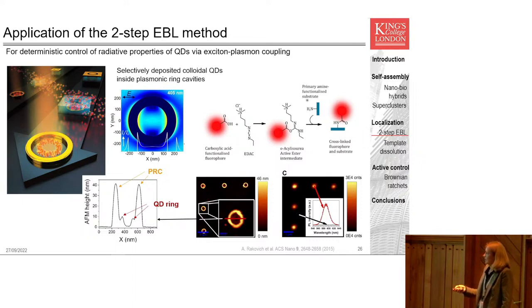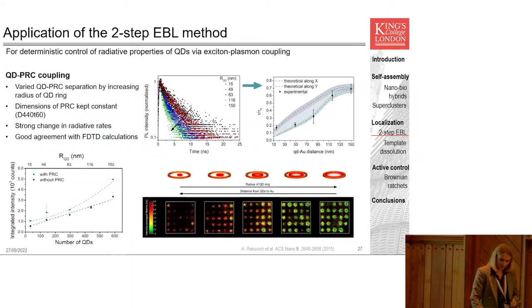And so in the same method, you can then place quantum dots on the inside of this plasmonic ring cavity to make them couple to the plasmonic structure. And here I'm showing an AFM image of the plasmonic ring cavity, which is 40 nanometers high, which is these two peaks here in cross-section. And there's a ring of quantum dots deposited inside, which is this little blip here in the AFM data as well. You can clearly see that you get emission from the quantum dots, so they're not affected by the process of this deposition method.